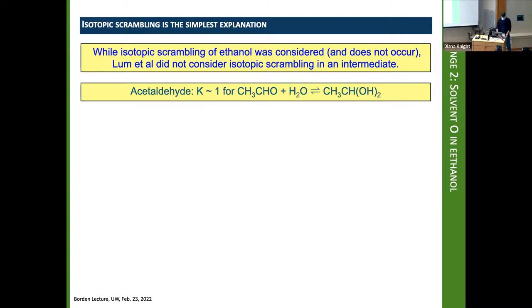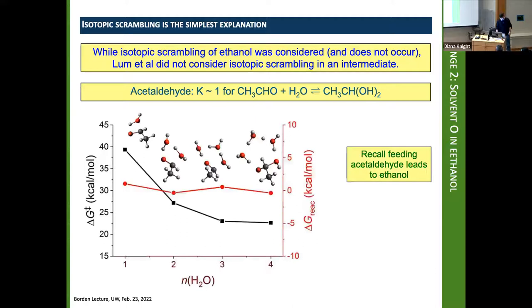All right, so we then dug through our list of intermediates, and we began thinking about the hydration of acetaldehyde to make a diol, and then the dehydration to lose water. It'd be a very easy way to get the oxygen-18 into the acetaldehyde intermediate. And remember the other experiment: if you feed acetaldehyde, you make ethanol. So a little data: the activation energy on the left axis in black, the thermodynamics in red, little cluster calculations showing you that the equilibrium constant is on the order of one.